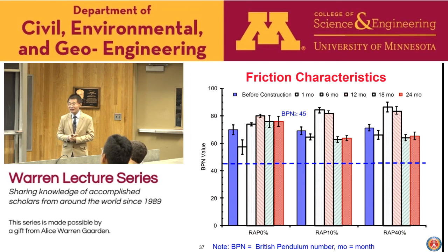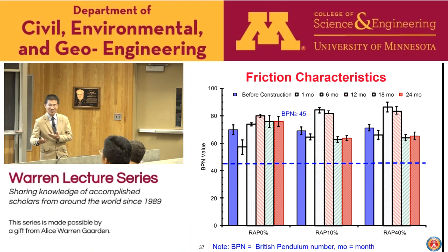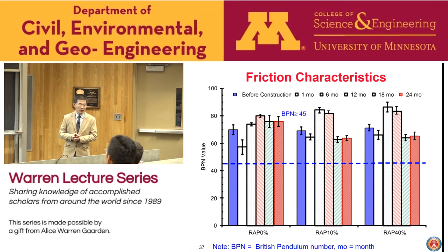This figure shows that the initial BPN value right after construction was a little bit low in the beginning, but the pavement skid resistance improved after the test section opened to traffic because the asphalt film coating the aggregate disappears after it's open to traffic. A BPN value higher than 45 is considered safe and sufficient for roadway. According to the test results here, all test sections provide good wet weather friction.